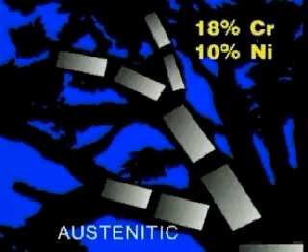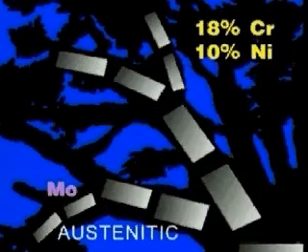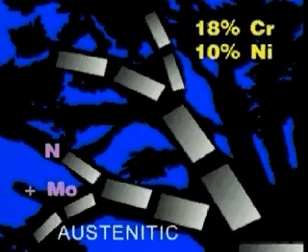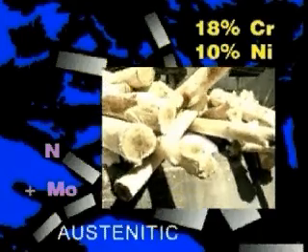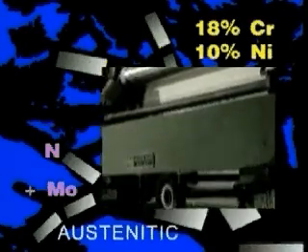So, stainless steels containing molybdenum are specified for this environment. Adding more molybdenum and some nitrogen further increases the steel's resistance to pitting corrosion, making it suitable for the very aggressive environments encountered in paper pulp production. Here, logs from renewable managed forests are being used. The wood fibers are broken down by both mechanical and chemical methods to produce these continuous sheets of pulp.